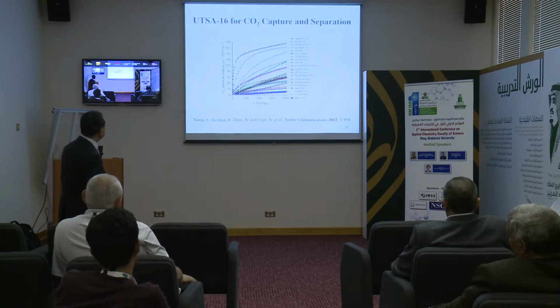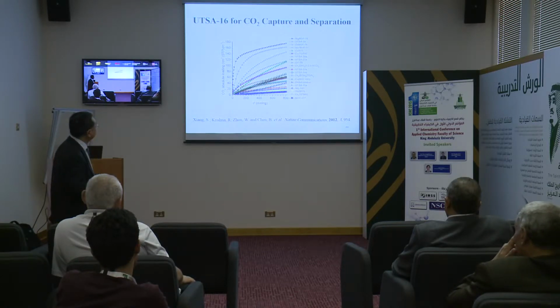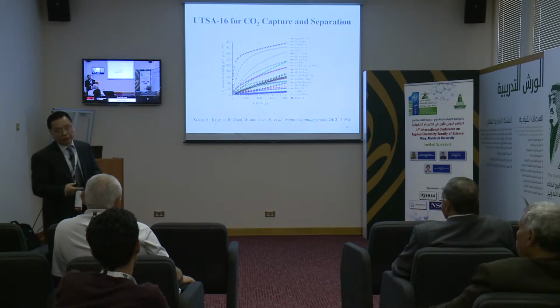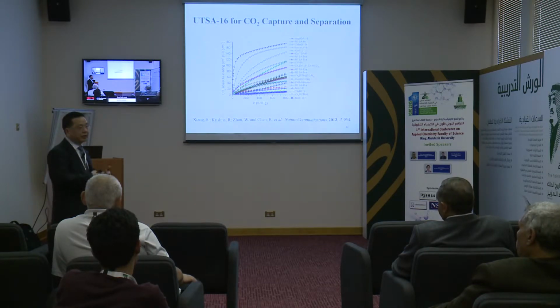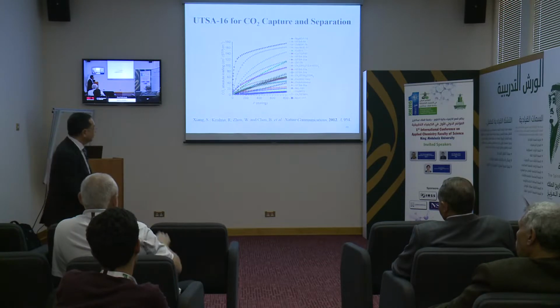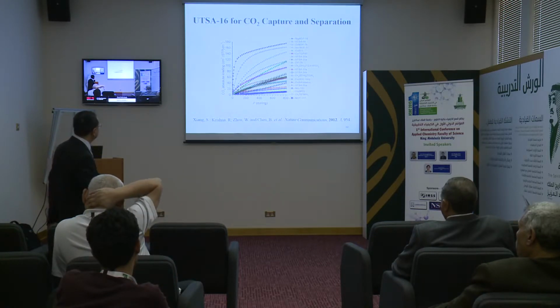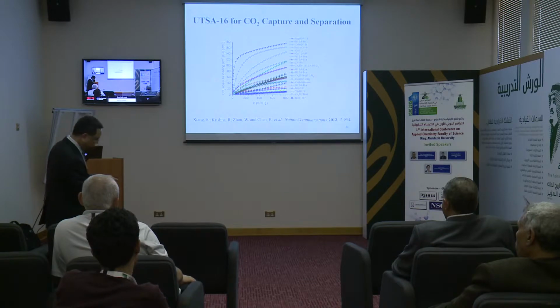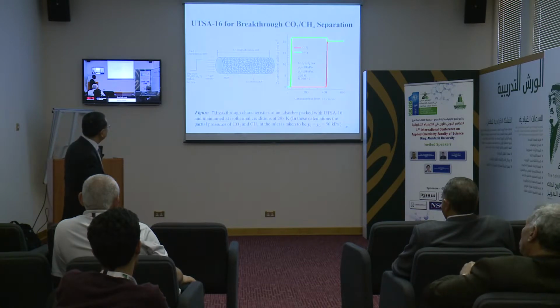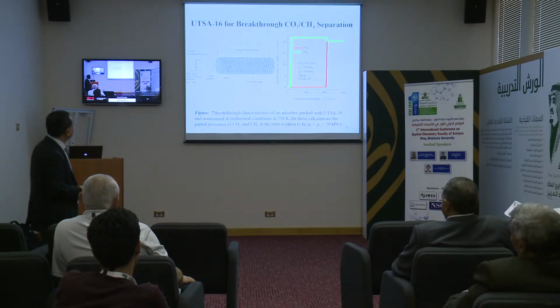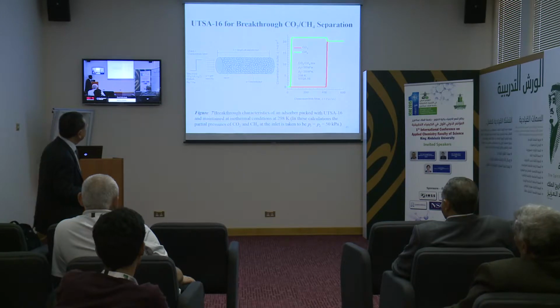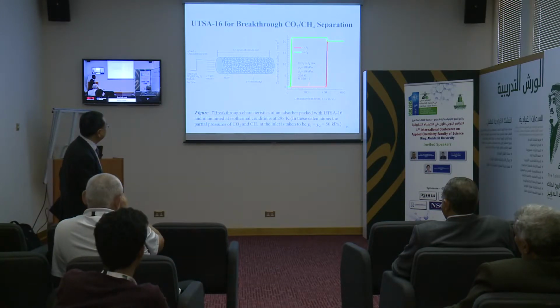And carbon dioxide capture is challenging for post-combustion applications, mainly because it is only one bar. For high pressure, the high porosity will of course enforce the separation, but the low pressure is challenging. We accidentally realized a unique material, UTSA-16, for this carbon dioxide capture, and the uptake is quite high. Although later on, Mohamed also reported several very high-performing materials for this carbon capture and separation. So this high uptake, of course, will enforce these separations.